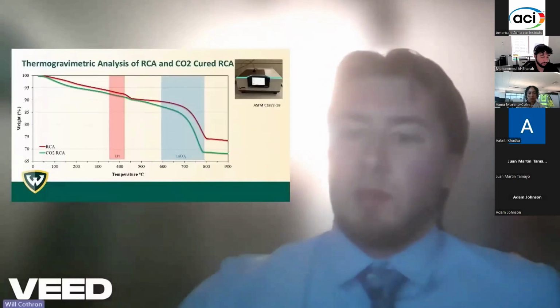These TGA results clearly demonstrate that the carbonation process effectively converted calcium hydroxide into calcium carbonate. This chemical change densifies the surface of RCA as shown from the reduced water absorption in the previous slide.